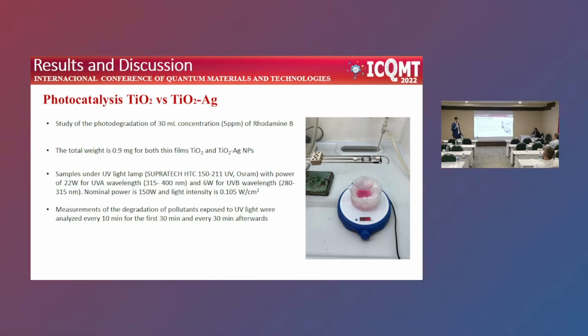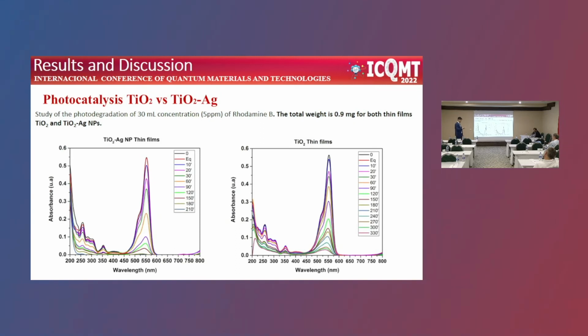It's too low in comparison with other works that are published nowadays. So we apply UV light. This is the type of light that you use, and we measure the degradation of the pollutant exposed to the UV light during 10 minutes for the first and 30 minutes afterwards in order to analyze how it can degrade the pollutant. Well, the difference between the titanium oxide thin films, in order to compare the titanium oxide with silver nanoparticles, is too high. Observe the times.